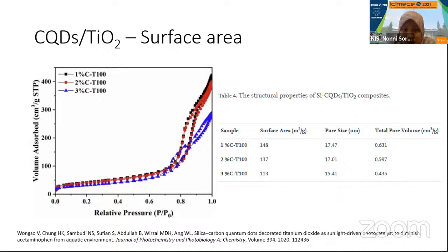Based on the surface area, we found that the surface area of the titania can be improved when we incorporate the carbon quantum dots into the matrix of the titania. Okay. So we see that the surface area is optimum when we incorporate 1% of the carbon quantum dots. Right? But with further increasing of the carbon quantum dots, what we found is the surface area is decreasing.